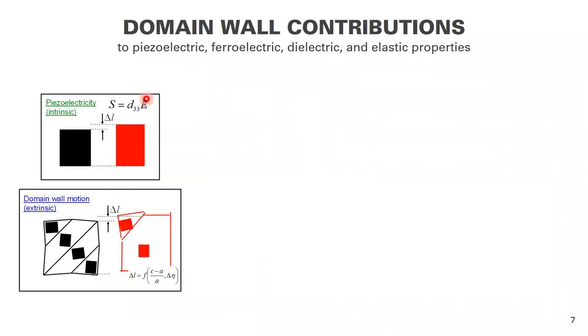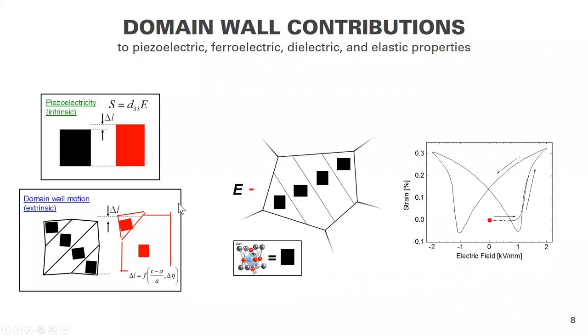And so if you draw some simple schematics, you can get an appreciation for what the intrinsic effect may look like for piezoelectricity, and then also how the extrinsic effect may also contribute to macroscopic strain. If you change the volume fractions of these respective domains, you get a net effect on macroscopic strain. And I like to draw this a little bit more from a microstructural perspective in this schematic. And what we're going to do is we're going to apply increasing amounts of electric field and move these domain walls and see how it tracks against the strain field hysteresis loop.